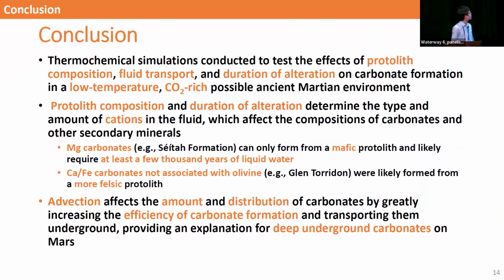So in conclusion, we conducted thermochemical simulations to test the effects of protolith composition, fluid transport, and duration of alteration on carbonate formation in a possible ancient Martian environment with low temperature and a carbon dioxide atmosphere. And we show that protolith composition and duration of alteration can control the compositions of carbonates and other secondary minerals. We found that magnesium carbonates can only form from a mafic protolith and likely require at least a few thousand years of alteration by liquid water.